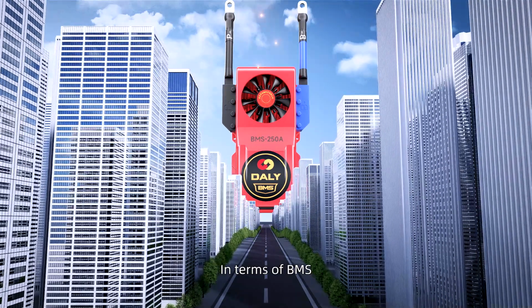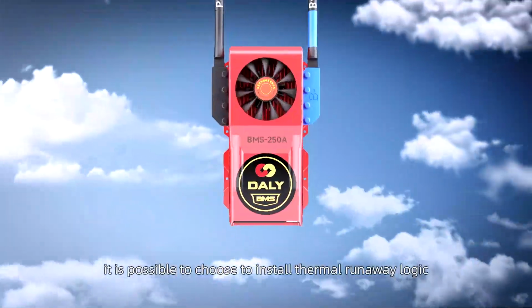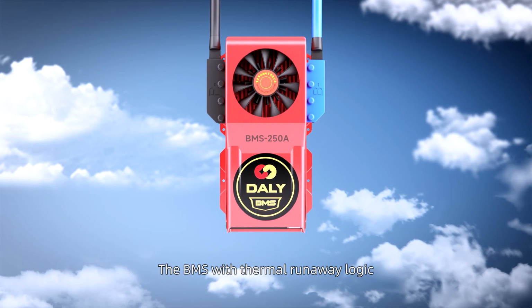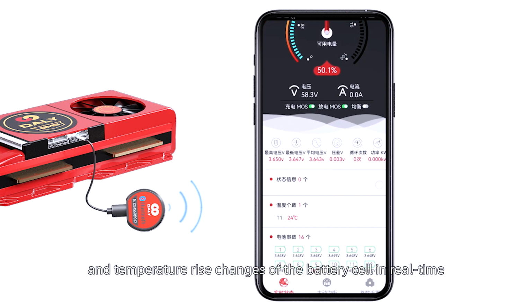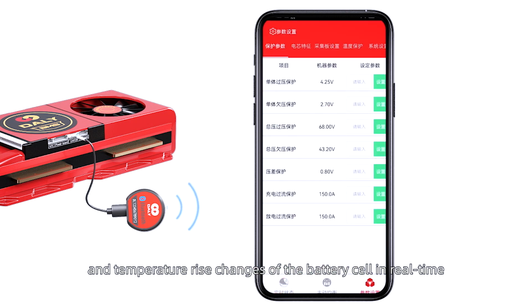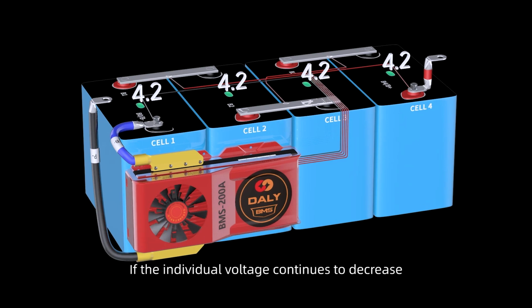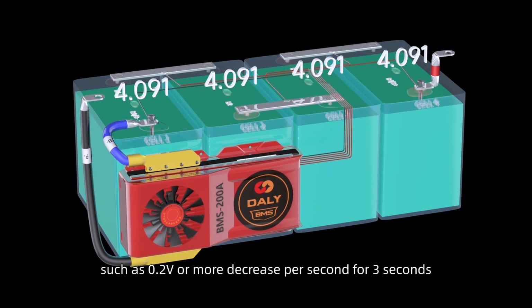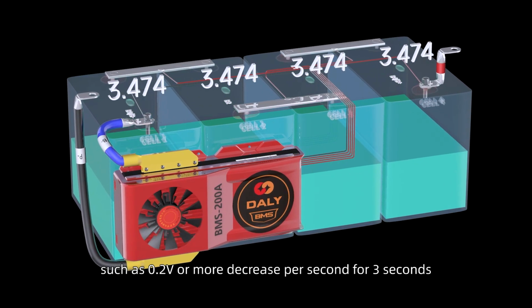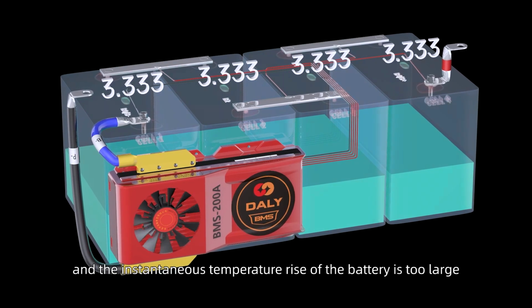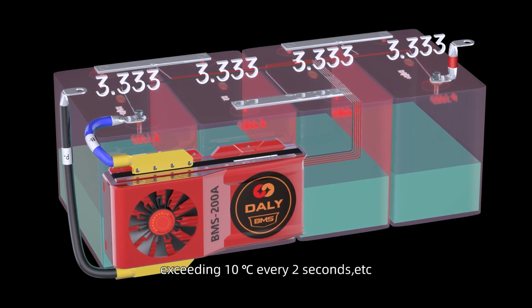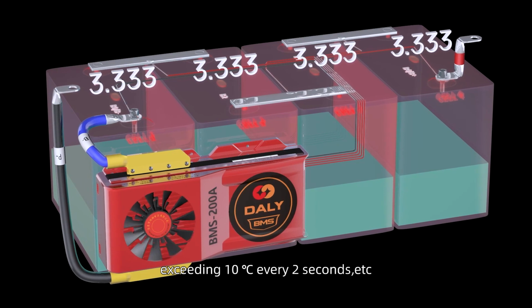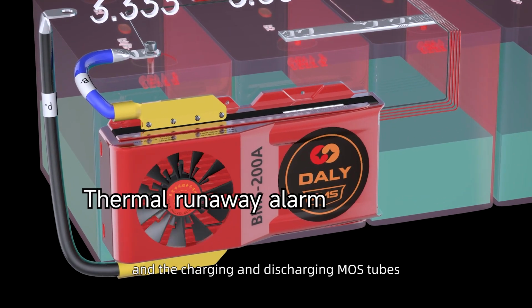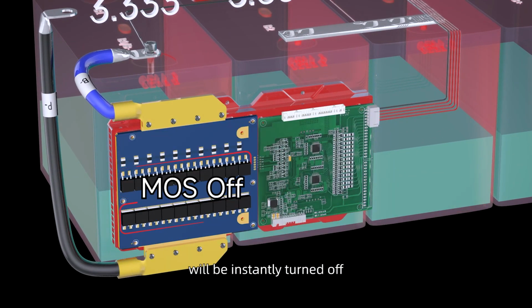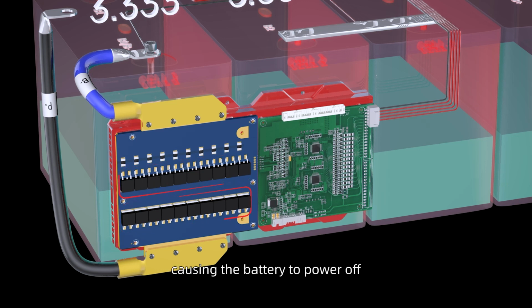In terms of BMS, it is possible to choose to install thermal runaway logic. The BMS with thermal runaway logic will monitor the voltage and temperature rise changes of the battery cell in real time. If the individual voltage continues to decrease, such as 0.2 volts or more per second for 3 seconds, and the instantaneous temperature rise of the battery is too large, exceeding 10 degrees every 2 seconds, etc., a thermal runaway alarm will be triggered, and the charging and discharging circuits will be instantly turned off, causing the battery to power off, thereby preventing further danger from occurring.